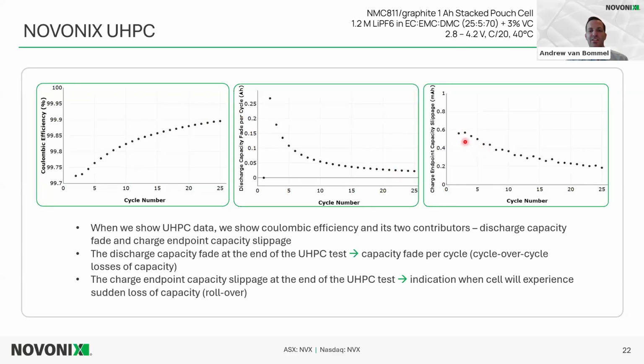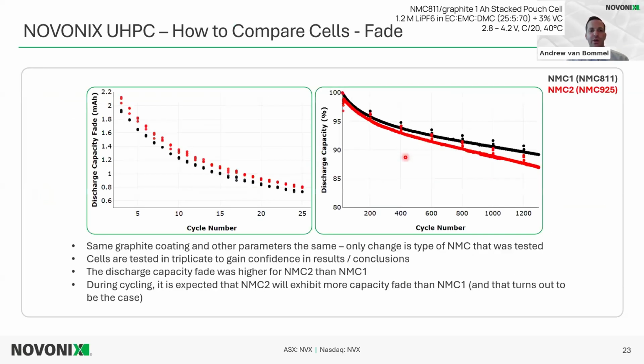So the use of this is comparing a few cells. If we see slippage is higher for one cell than the other, this can indicate that it would have the sudden loss in capacity, or rollover, quicker than the other cell. And then if we see fade is higher for one than the other, we say the fade in normal cell cycling will be higher as well. And we can check this with long-term cycling as well. But NOVONIX UHPC really gives us that confidence really quickly in how the cells will perform.